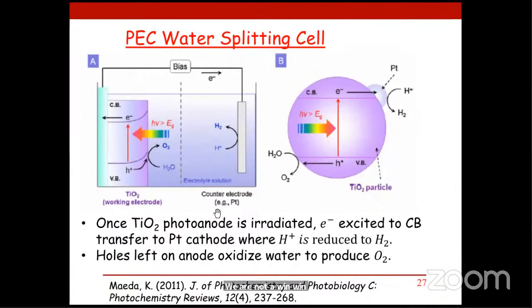when we irradiate with the solar radiation, we get electrons to the CB, which are transferred, you can see from here, to the cathode. Then holes are left on the anode, which oxidize water to produce oxygen. So we have an oxygen evolution reaction on the photoanode, and then a hydrogen evolution reaction on the cathode. Now, usually the oxygen evolution reaction requires a large overpotential, and therefore it's usually the major obstacle in this process.